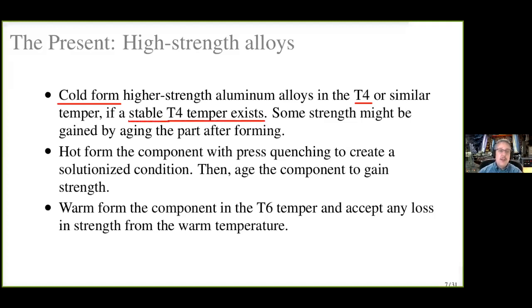So this issue of T4 temper is only good if it's stable. If we take 7075, it doesn't have a stable T4. If we quench it, it'll begin to naturally age. So if we wait more than a couple days, that material is now altered so that we can no longer age it to full T6 strength. So that's a real problem. It's not a process that's available for all alloys. And this is one of the reasons that the higher strength 6000 series are currently used, because many of them do have a stable T4 temper. But the much higher strength 7000 series alloys are not used in automobiles currently, largely because they can't be formed by the cold forming processes that require T4 temper.